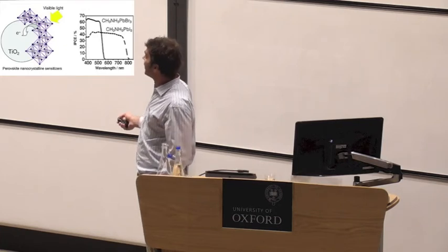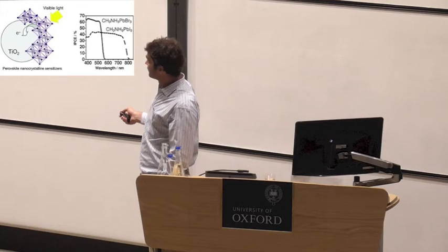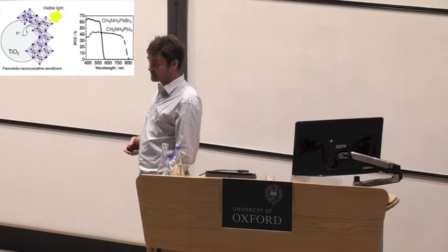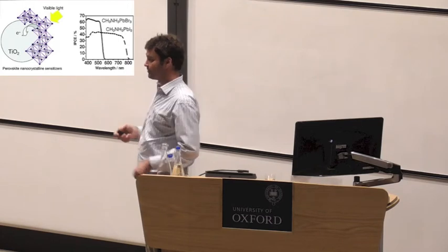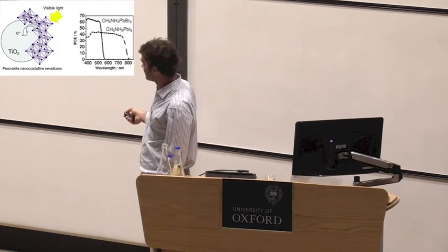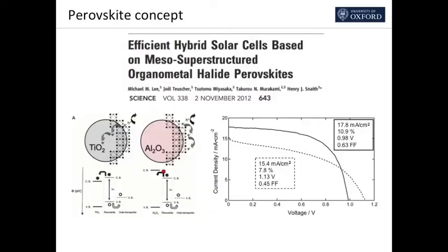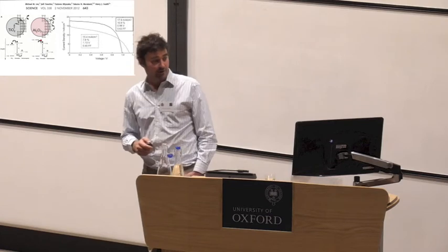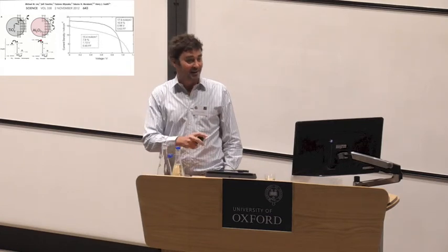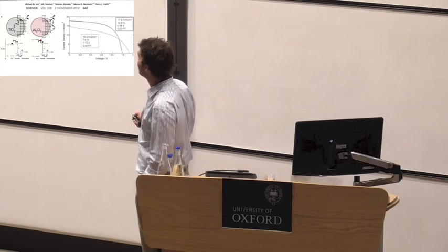In 2009, a colleague in Japan reported the first perovskite-sensitized solar cells. Again, this is one of this bulk heterojunction, distributed junction, using perovskites as an absorber to replace an organic dye. We started working on this technology in collaboration with this Japanese colleague, and what we discovered was we didn't need this separate TiO2 that was an N-type, the negatively charged semiconductor. We could get rid of it and just use an insulating scaffold. Again, I won't go into the details. I'm trying not to lose you all here, but the efficiency improved. What we got was a big jump up in voltage.